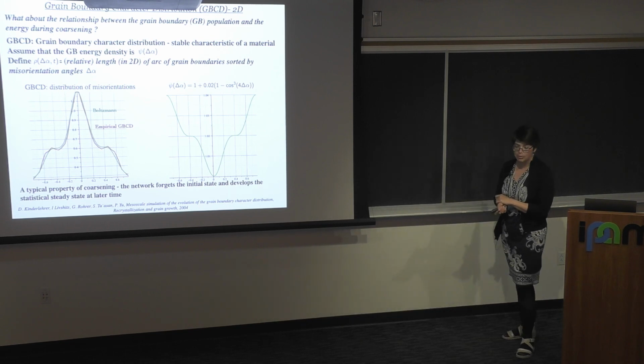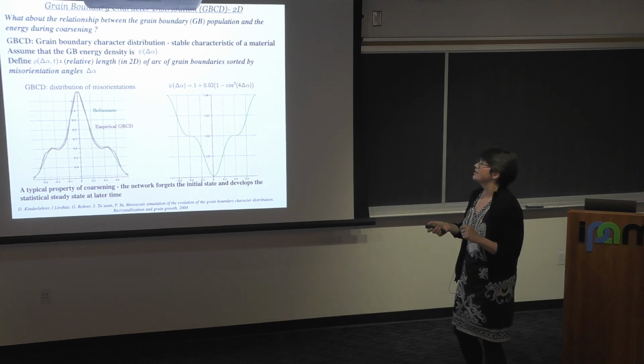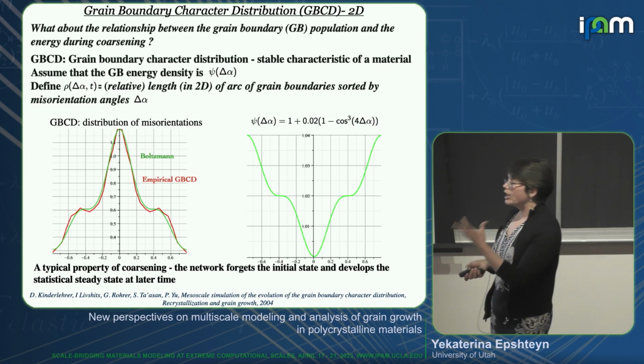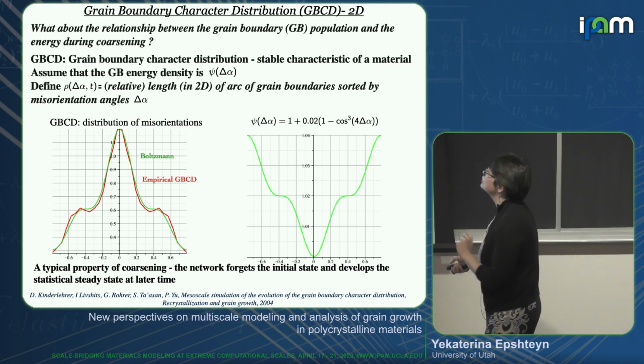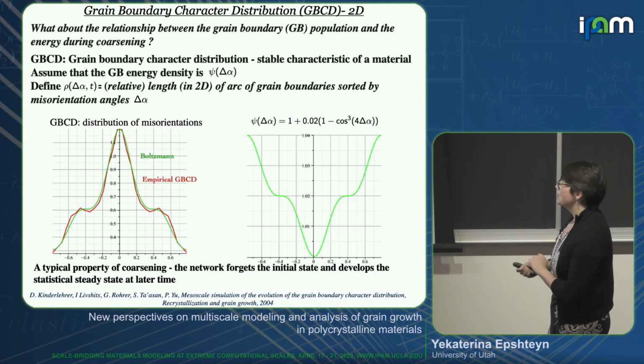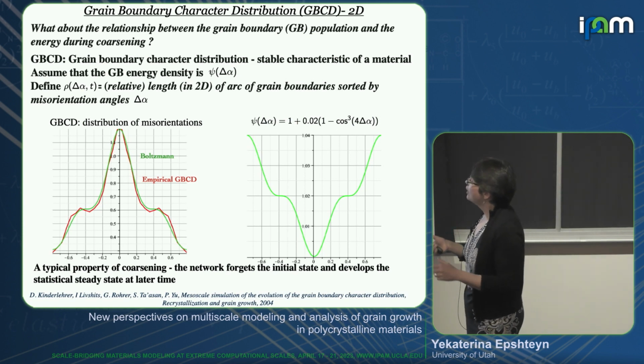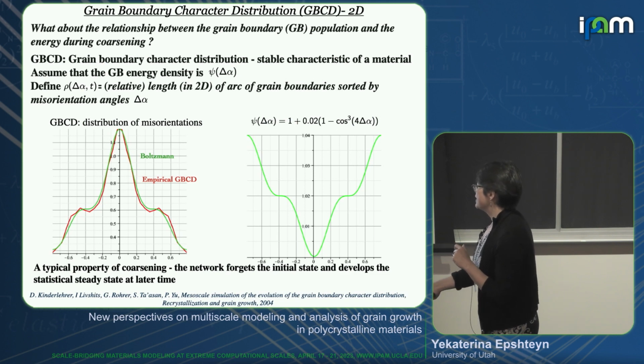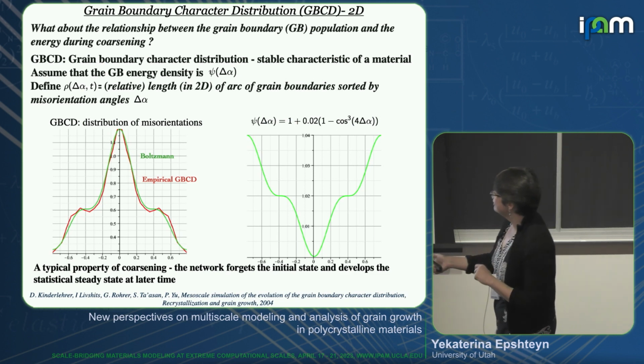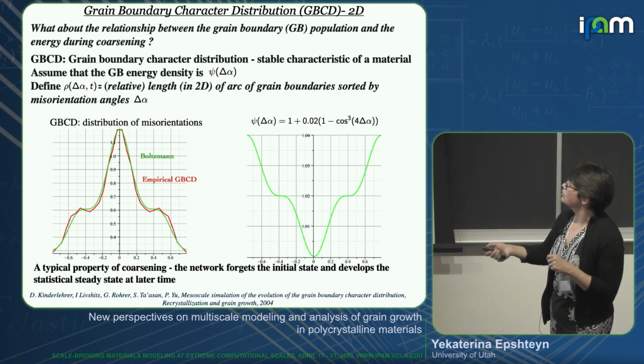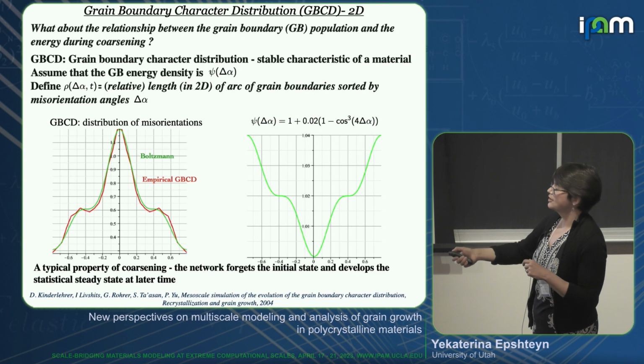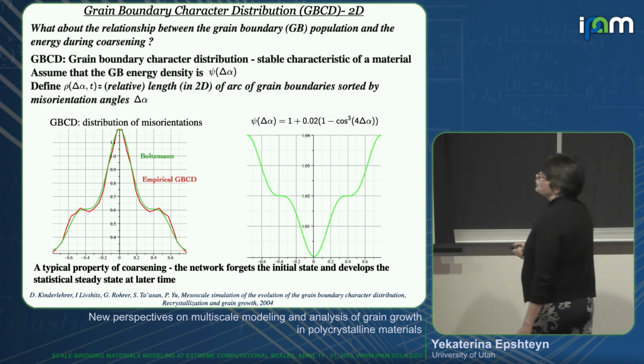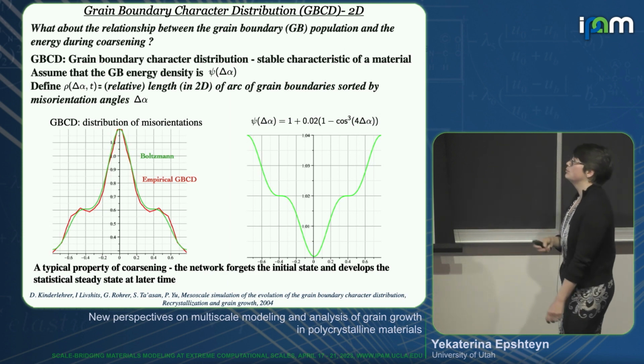So I showed how the total energy decays with time. But no less important is the question of how to classify grain boundaries with respect to energetic properties during grain growth or during coarsening. And for that, it's important to figure out some reliable metric. Such a statistic was found quite a long time ago, discovered at Carnegie Mellon in both numerical simulations and experiment. It's known as the grain boundary character distribution, or GBCD, which was found to be a stable characteristic of the material.